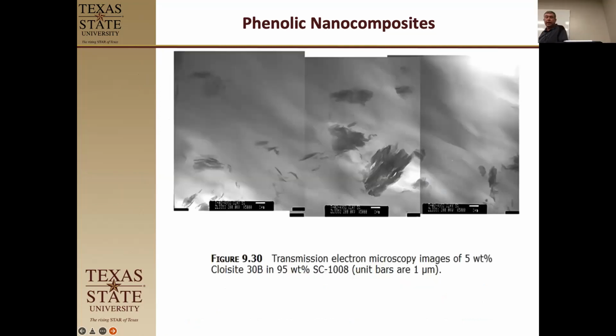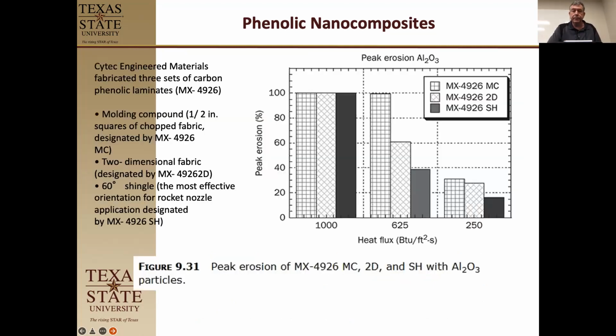Okay, so then they tried to say, our montmorillonite should be better than that. So they tried to disperse it a little bit more, and again, they got very poor dispersion. We call this poor dispersion. Large platelets here, some exfoliation here. They're probably not using a good method. They were just using a stir method in their system, and that was not appropriate. For this, they stirred it in IPA for 30 minutes and then added their materials.